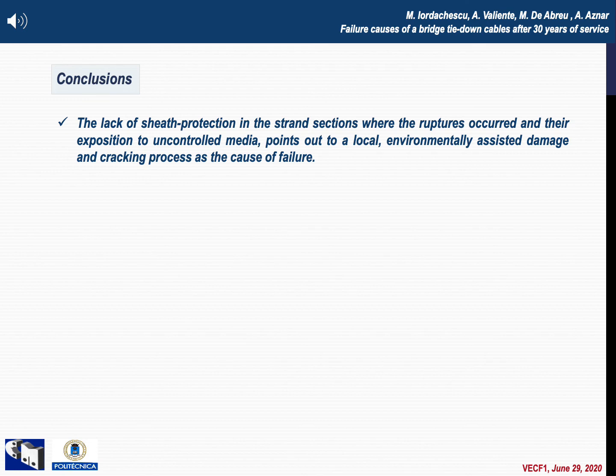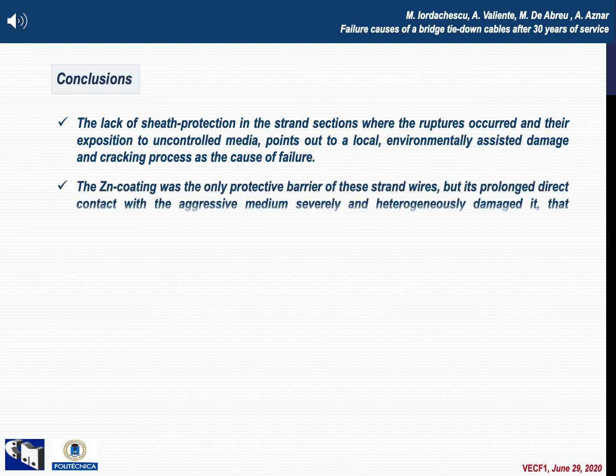The main conclusions of present research are: the lack of sheath protection in the strand sections where the ruptures occurred and their exposition to uncontrolled media points out to a local, environmentally assisted damage and cracking process as the cause of failure. The zinc coating was the only protective barrier of these strand wires, but its prolonged direct contact with the aggressive medium severely and heterogeneously damaged it, that propitiated the stress corrosion cracking of the wire steel.